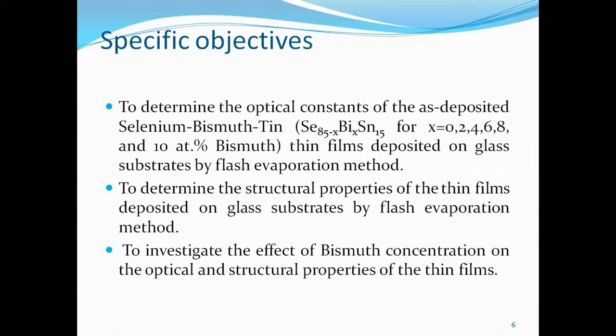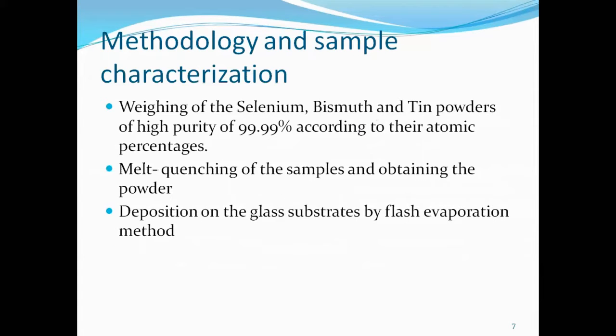Then the second specific objective was to determine the structural properties of the thin film. And the third specific objective, which is the last, of course, is to investigate the effect of bismuth concentration. On to the methodology and sample characterization. After obtaining the 3 powders, we made sure they are of high purity, of course, 99.99%. So after obtaining them, weighing was done according to their atomic percentages.